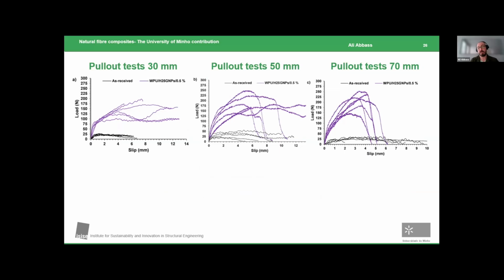You could see a tremendous increment in the pull-out load, overall six to seven times, and this is very impactful when we're talking about pull-out. Throughout the test, you would see that no matter how we increase the bond length for the non-coated fibers, the pull-out response was pretty much the same. No improvement, no changes technically. For the coated fibers, you would see at 30 millimeters a typical pull-out response, while when we move to 50 and 70 millimeters, we have fiber rupture. So this tells us it's not a pull-out test anymore. It's a tensile test, actually.